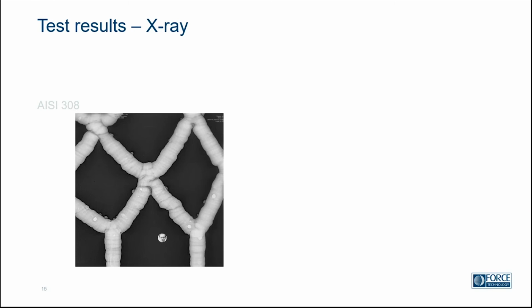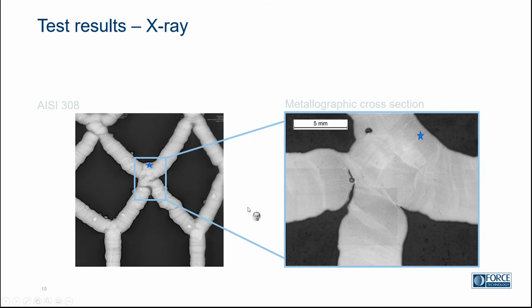Because we also often want to do these complex geometries and use minimum material, we have here made a wireframe structure, and this is actually photographed with X-ray, meaning that we are looking at differences in the material thickness without destroying the material. We can see some indications that we have maybe less material in this section, where in the idealized design this could be identified as a critical point, and maybe it's even more critical now because we have the appearance of a small crevice. For the sake of illustration we then cut it up, and as you can see here from this metallographic cross section, we do indeed have a crevice, which can be critical from a mechanical standpoint but also from corrosion.